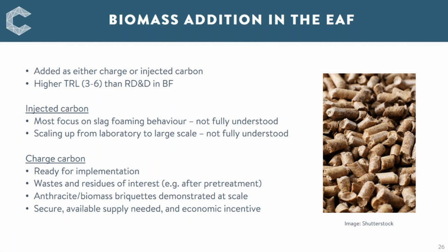The other place that biomass is being used is in the electric arc furnace. There's been a lot of studies in this area, and actually at quite larger scale, because it's a batch process. It's easier to study in that system. It's smaller scale than a blast furnace. It's a batch process, so it's easier to undertake trials. And the biomass has been added either as charged carbon or as injected carbon. And most of the focus for the injected carbon, as I was saying earlier, is understanding how the substitution of coal for biomass products affects this slag foaming behavior, which isn't fully understood.